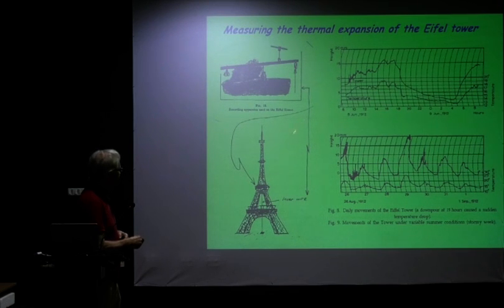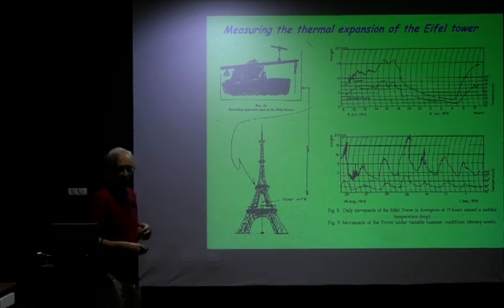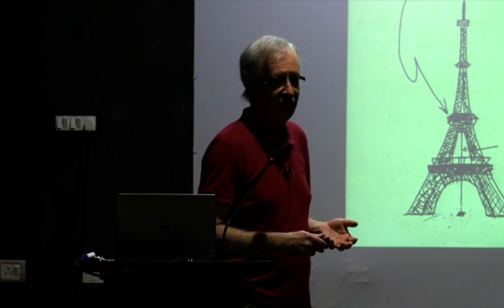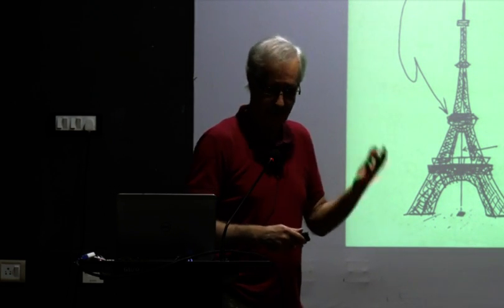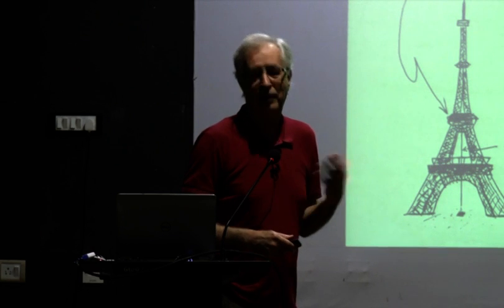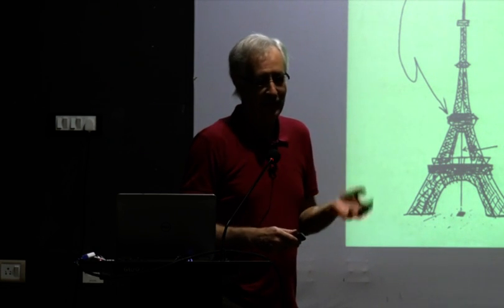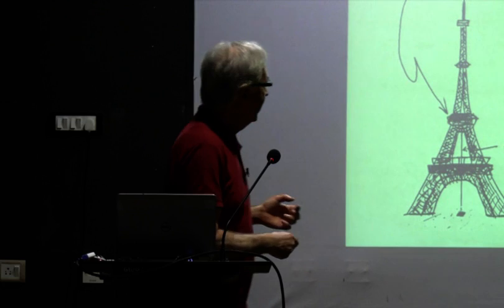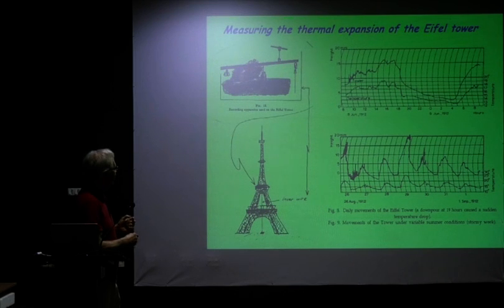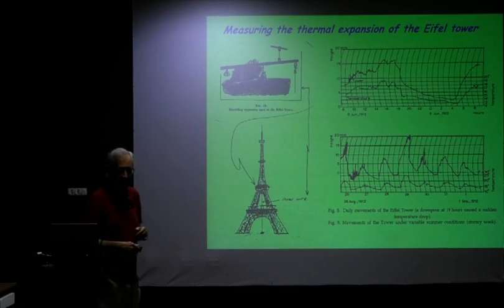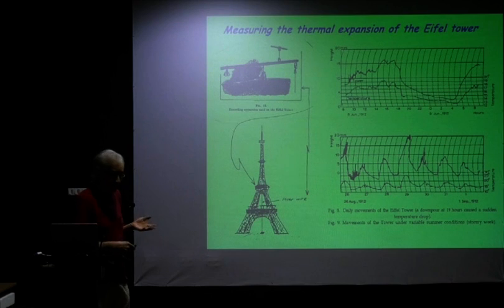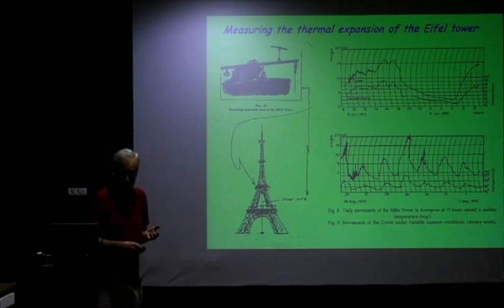So if this wire is Invar, and if the thermal expansion coefficient is 0, then this wire is not going to expand. The Eiffel Tower is going to expand, and you're going to have a recording here as this wire is constant and the tower is expanding. And indeed, they got very good data.